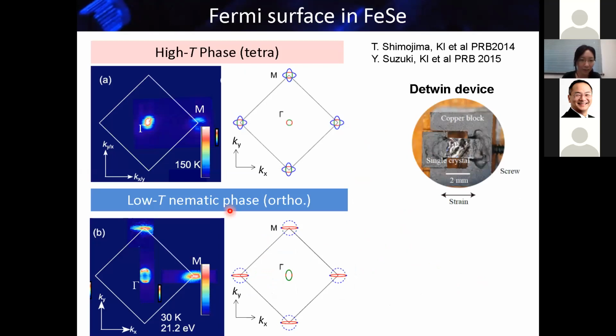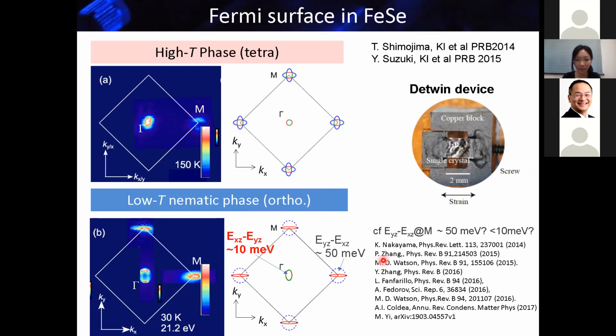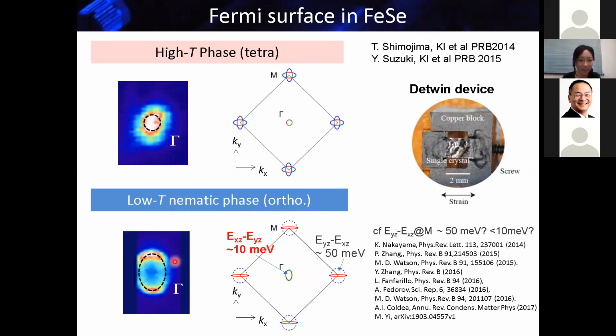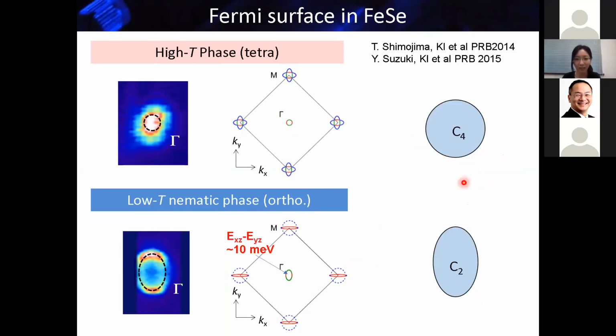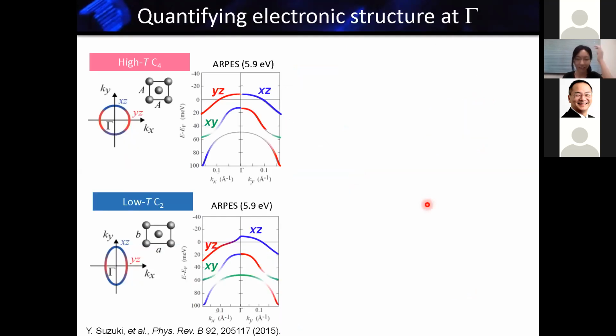By usual static ARPES, in 2014-15 we tried to clarify the nematic state in iron selenide, and we found that at high temperature the Fermi surface is four-fold symmetric like this. But when you cool down below the nematic phase transition, the Fermi surface changes into this elliptical shape, from circular to elliptical. It reminds us of the Pomeranchuk instability scenario. So we found this nematic state in 2014-15.